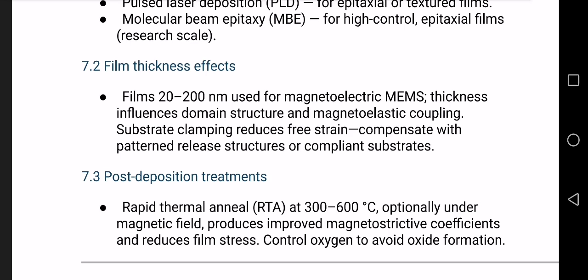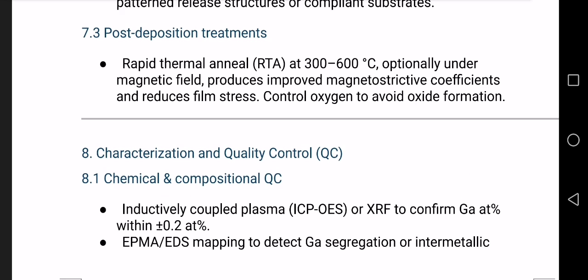Okay. Post deposition treatments. After deposition, films are not ready yet. They have residual stress, defects, and poor magnetic anisotropy. Okay. Rapid thermal annealing, RTA. Typical RTA conditions are temperature 300 to 600 degrees Celsius, short time exposure. And what are its effects? Stress relaxation, improved magnetostriction, and better domain alignment.